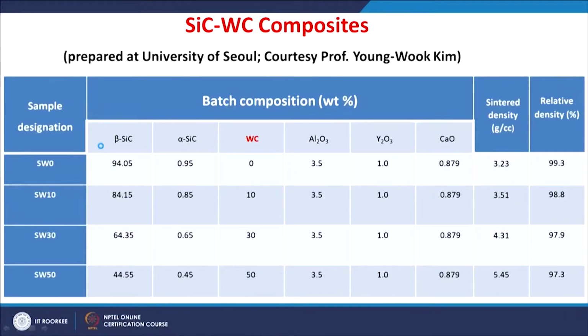These silicon carbide tungsten carbide composites were prepared at the University of Seoul with the support from Professor Youngwook Kim of University of Seoul. Four composites are selected for the present study with varying tungsten carbide content from 0 to 50%. So, 0, 10, 30, 50 weight% tungsten carbide containing silicon carbide ceramic composites are prepared with beta silicon carbide with a small amount of alpha silicon carbide and aluminum oxide, yttrium oxide, calcium oxide as additive systems.